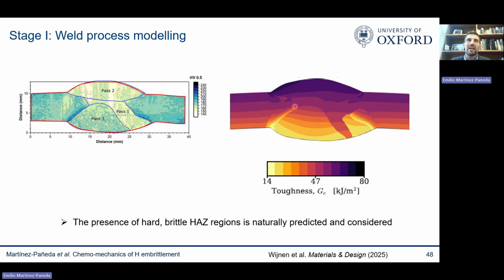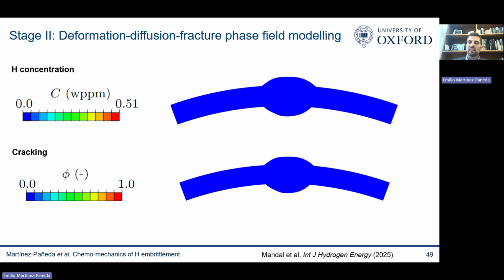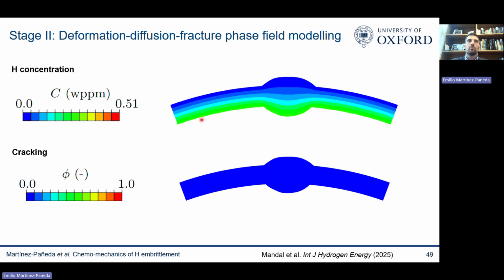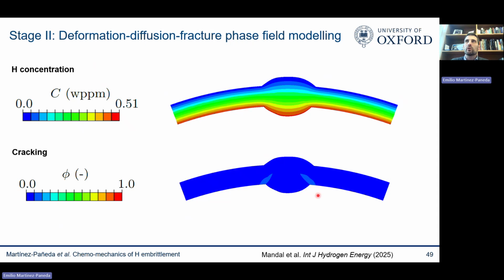So then we use this, because now we naturally know what is the distribution of properties and therefore the susceptibility to having - we naturally capture the fact that this heat-affected zone is going to be more susceptible. So we basically now ramp up the pressure. You can see here we're ramping up the pressure, we see the hydrogen distributing, and at some point you will see here that a crack forms. When we reach a critical pressure, the crack will grow and the entire thing will fail.